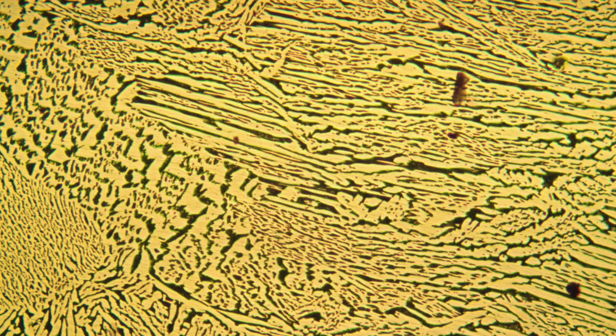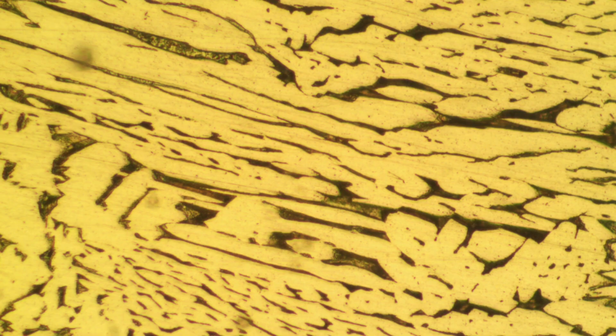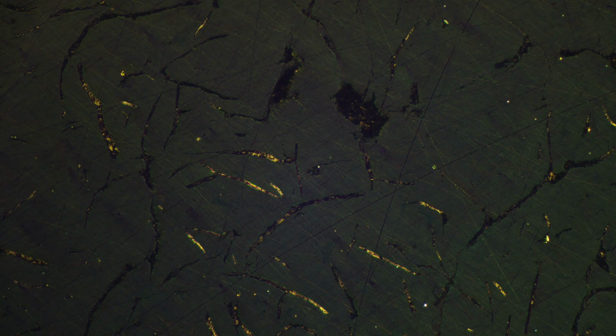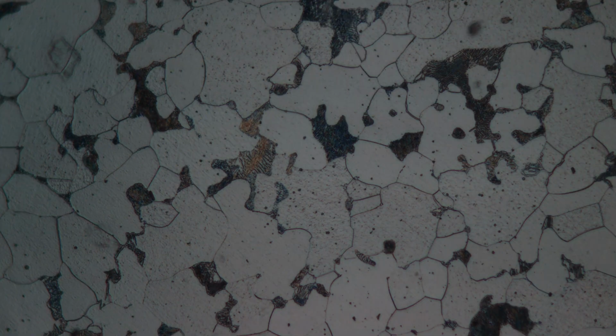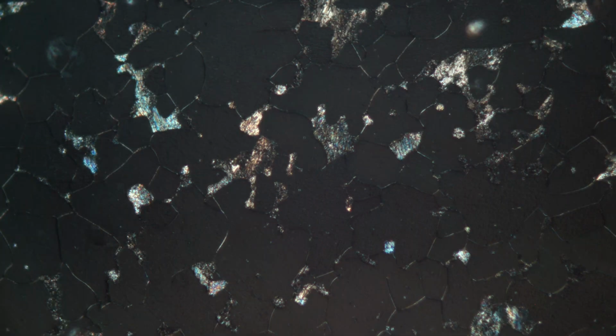Bright field provides a reliable, magnified image of the object. Simple polarization reveals polymers, contaminants, and foreign inclusions, and also increases image contrast. The examination is based on the optical anisotropy of the inclusions. To set it up, you need to position the polarizer so that the field of view becomes dark. Then adjust the brightness of the illumination. Its level should be close to maximum. In this mode, the desired inclusions become most noticeable.